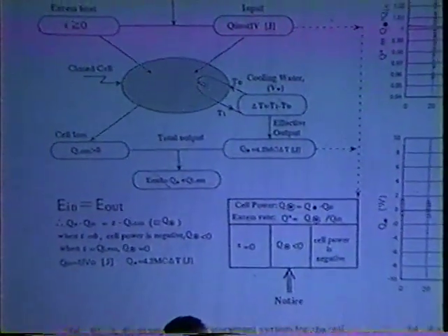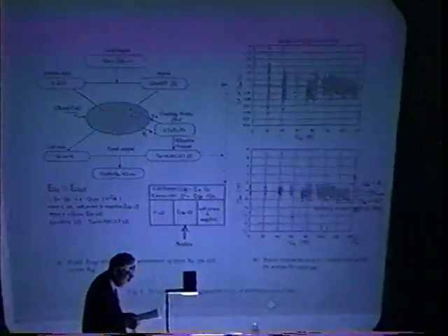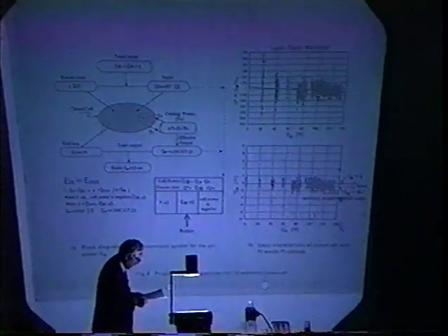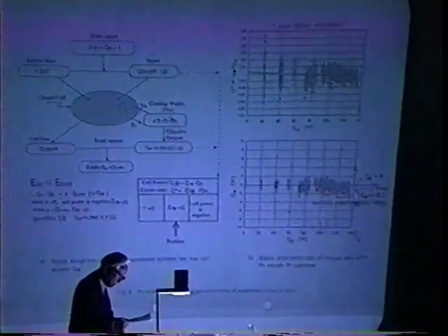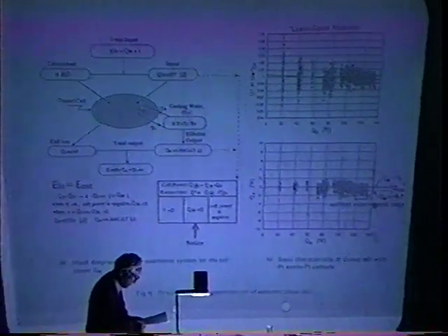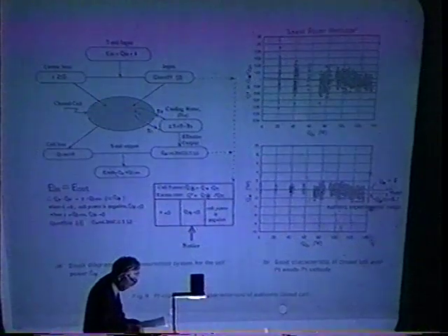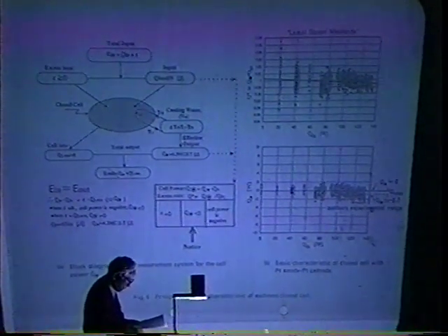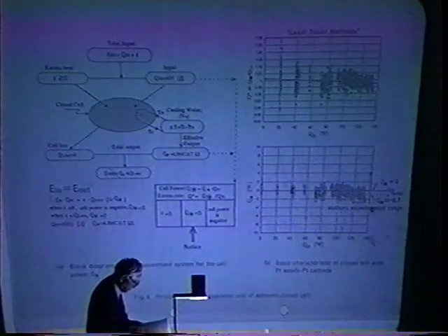in this one. Right side is inherent feature of our closed cell and indicates the most important basic data using platinum anode and platinum cathode. Our usual experimental range is around 120 to 150 watts, and the cell power is clearly negative with about -1 watt as you see here. Our old data were obtained by only changing the platinum cathode to a PS cathode.